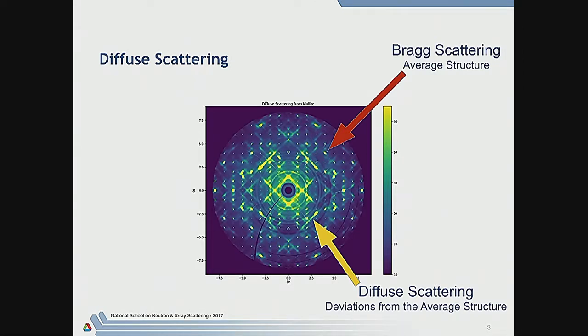So anyway, there's an awful lot of intensity that's highly structured and actually quite beautiful between the Bragg peaks. And this is diffuse scattering. It represents deviations from the average structure. So particularly with X-rays, that could be dynamic deviations, such as thermal vibrations, phonons. They will give rise to thermal diffuse scattering.